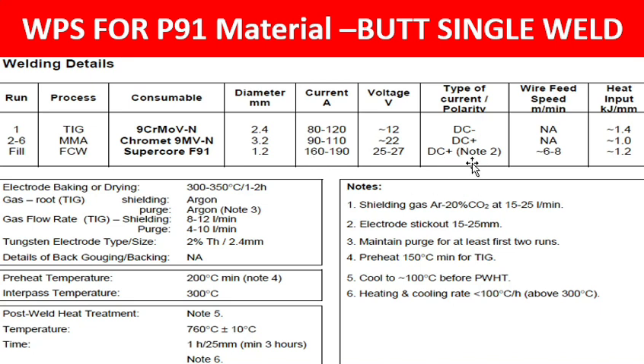Electrode stick out is 15 to 25 mm. We are using the electrode baking, same here, 300 to 350 degrees. Gas for TIG welding is argon, and the purge is also argon. Gas flow rate is the same, 8 to 12 liters per minute. Purge is 4 to 10 liters per minute. Tungsten electrode type and size is 2% thoriated, 2.4 mm.